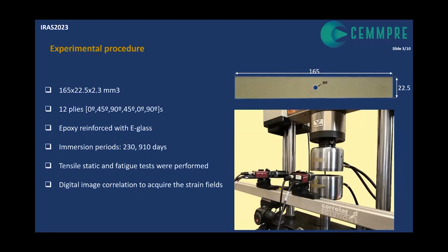In this work, we studied the effects of the marine environment on composite materials, and rectangular samples made of epoxy reinforced with E-glass were immersed in seawater and tested after periods of 230 days and 910 days of immersion. Tensile, static, and fatigue tests were performed, and digital image correlation was used to acquire the strain fields at the specimen surface.